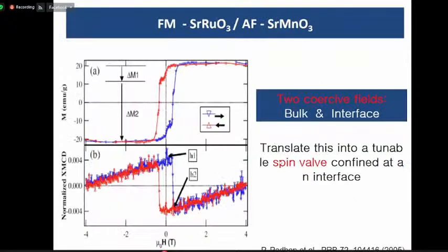My research is motivated by this result. In this result, they show two coercive fields like this. One is here, the other one is here. They said this coercive field is because of the pinning of spins at the interface. This one is from the strontium ruthenate, the ferromagnetic material, but at the interface it is pinned, so it becomes wider than before. So I'm interested in the interfacial spin.